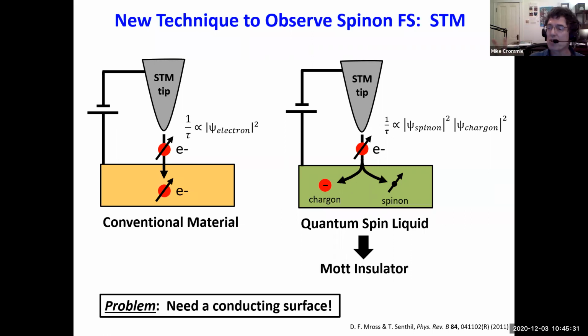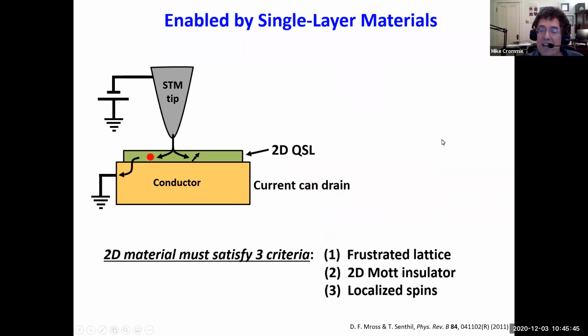And the reason, of course, is because quantum spin liquids exist in a Mott insulator. It's an insulating system. And so you can't do STM on an insulator because you've got to get the charge out. And if it's insulating, it doesn't work. You need a conducting surface. And so it turns out that a trick that you can do is that if you have a single layer, a two-dimensional quantum spin liquid, then you can tunnel into it, because now I can tunnel electrons in, they break up into spinons and chargons, but then I can drain them through a conducting substrate. If I put my two-dimensional quantum spin liquid on a conducting substrate, then in principle, I could observe the quantum spin liquid behavior.